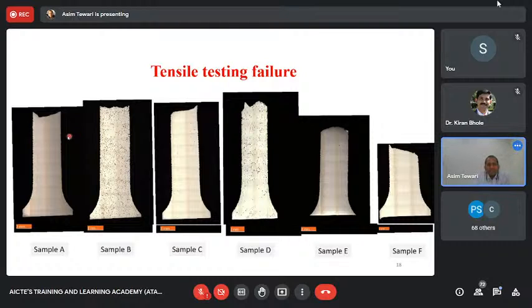So what we see is that these are the tensile tests of various parts made by additive manufacturing. Of course, what you see is not just a macro image, but a very fine microstructure image, compressed together to give you this. There is a checkered pattern, because these are collections of lots of images put together. One of the key things which is very clear is that they have a lot of porosity in them. We didn't try to do anything to reduce porosity; we just went with it as it was. You can see black spots here, black spots here.